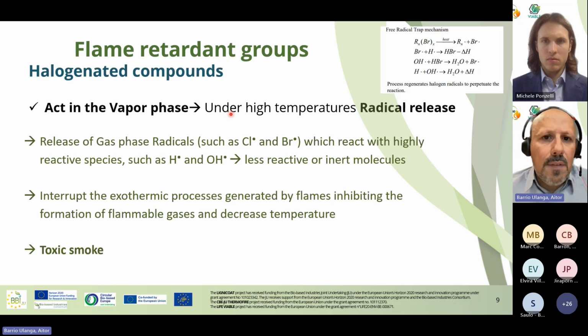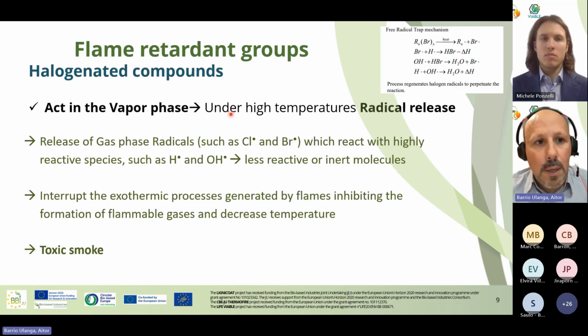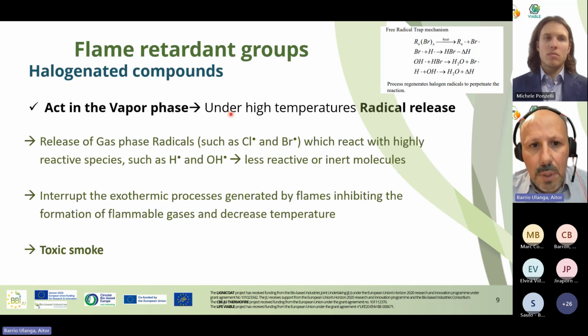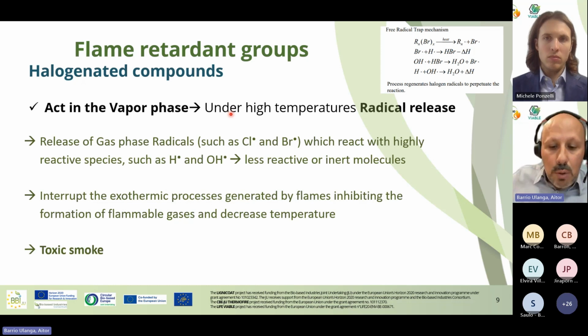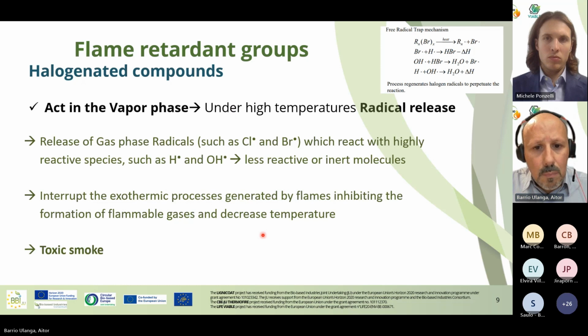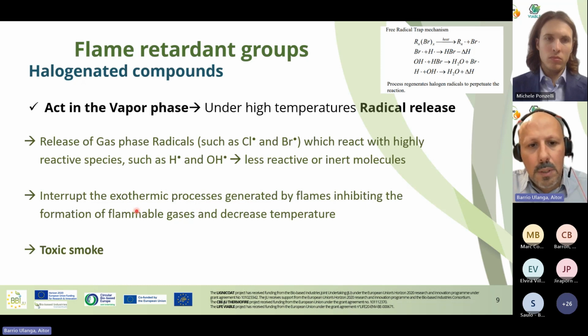What about the mechanism of the fire retardants? As commented, there are some fire retardants that act in the vapor phase, the very well-known halogenated compounds, which are the most efficient fire retardants because they release radicals that react with the radicals in the gas phase and inhibit the flames and decrease the temperature. These were very important in the previous fire technologies, but they are toxic. They produce toxic gases and they are inherently toxic. So the tendency in fire retardancy is to avoid the use of halogenated compounds, but there are some cases where it is still used.